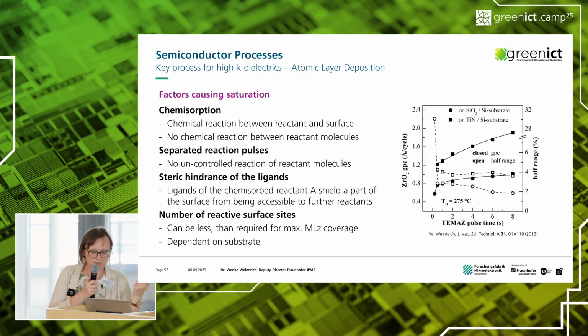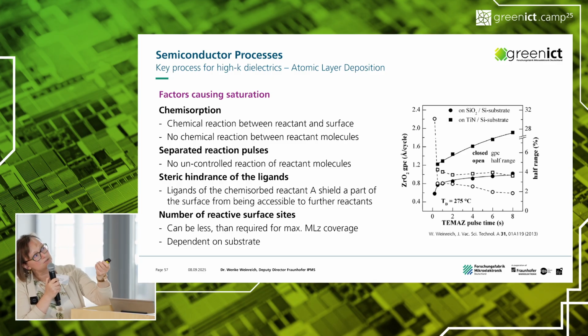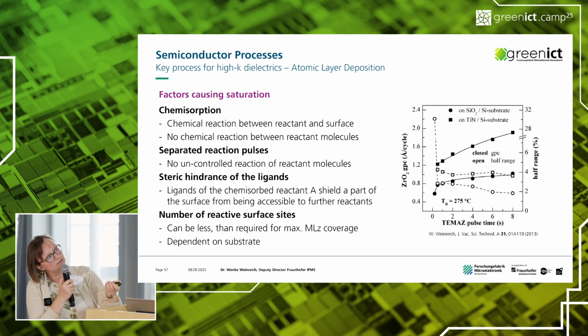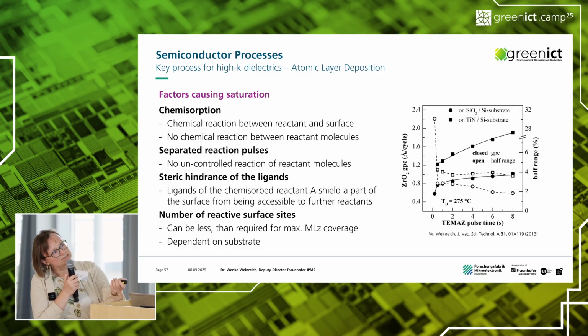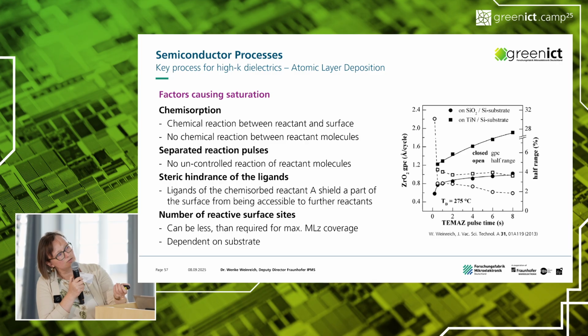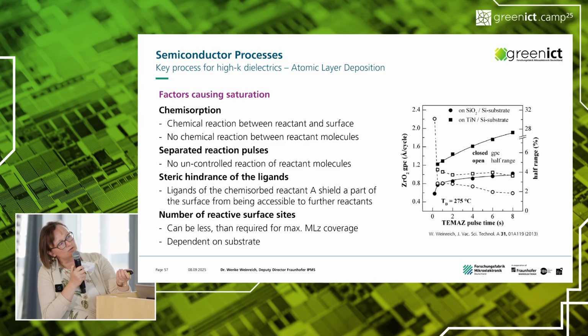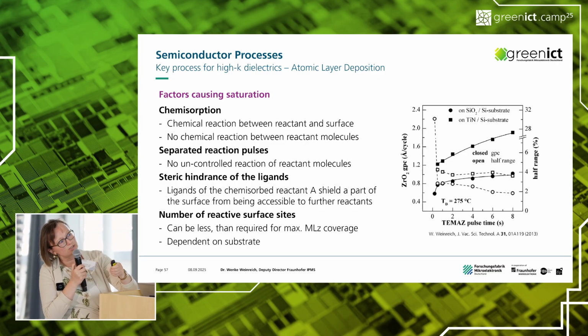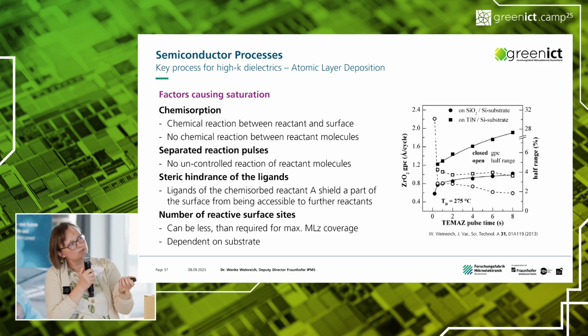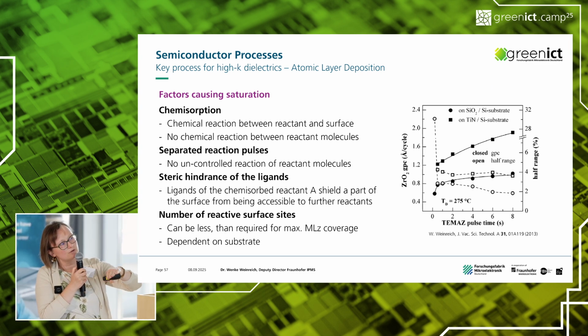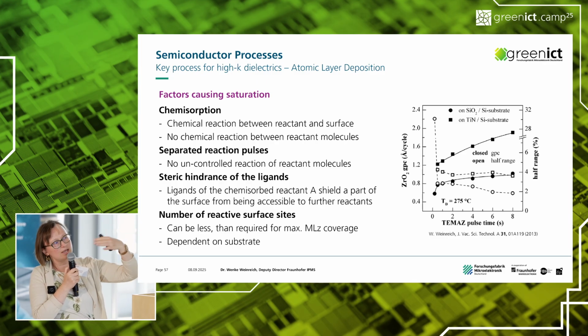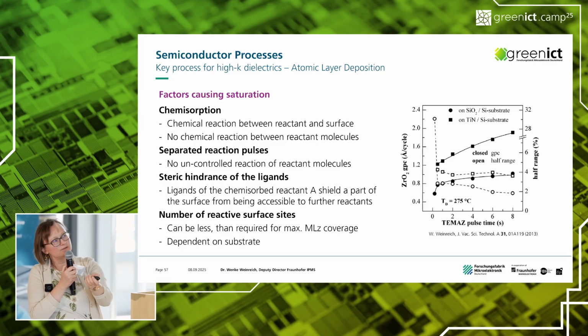I have here only one example for you, for such a simple deposition of zirconium dioxide on different substrates. And you can see here on silicon oxide, it's this saturation curve. Saturation curve means you bring material inside a reaction chamber only for 1 second, or you leave it in the chamber, for example, for 6 seconds. And if you have a saturation, that would mean you have only one layer on the surface, but you will not bring more layers on top. Doesn't matter how much material you have in your chamber, and that's really the case here.